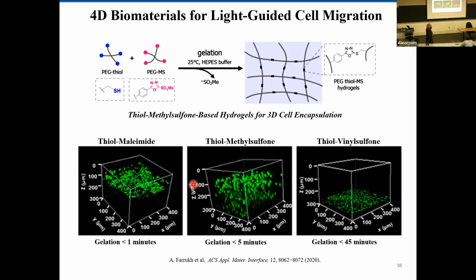To do that, we see in literature these PEG hydrogels, maybe you have heard about these. These are really famous for making 3D functionalized surfaces. But when we are trying to make hydrogels where you have cells inside, it means that you need to do the cross-linking while you have cells. That means that the cross-linking chemistry should be cell-friendly. It should not end up killing the cells. So in that case, we have two types of chemistry: thiol-maleimide and thiol-vinyl sulfone chemistries, but there are issues with both of them.